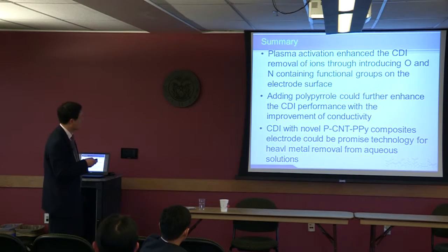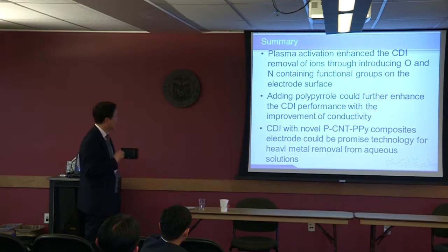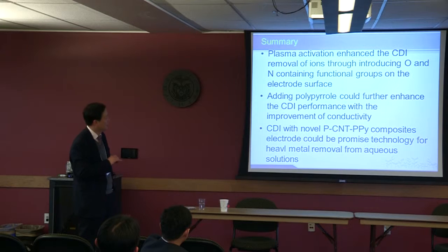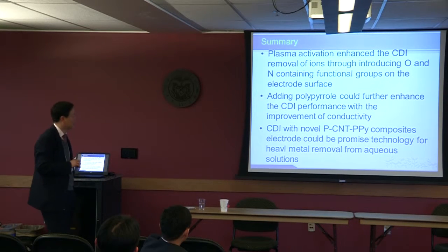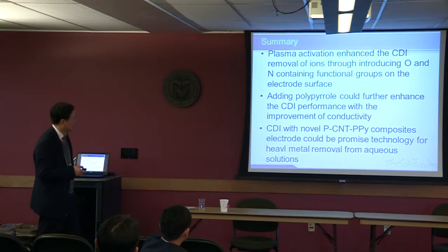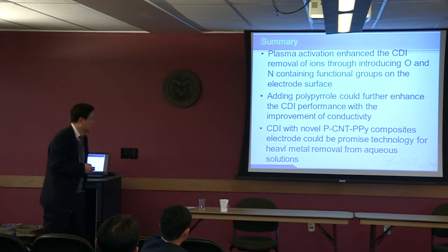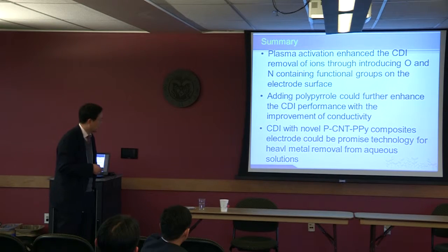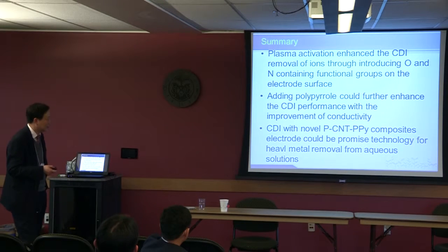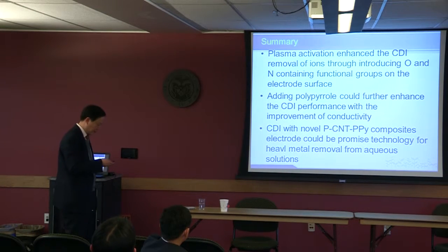The second point, doping with polypyrrole can further enhance the CDI performance through improvement of the conductivity. The third one is that this kind of technology could be promising for the removal of heavy metals from aqueous solution.